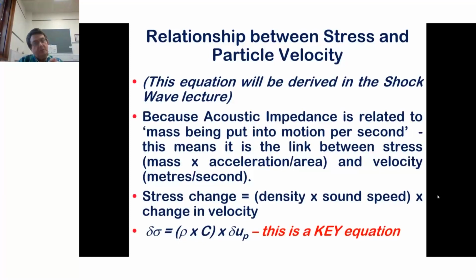And when I go into a shock regime, when I go to very high pressures, then the sound speed of the material changes. And that means that the term C stops being C and becomes something more complex. Not generally very much more complex, but it becomes a term that is stress dependent. But simple equation: change in stress equals density times sound speed times change in velocity of the particles in the material. And that means you can start to track what's happening at interfaces and what's happening within materials.